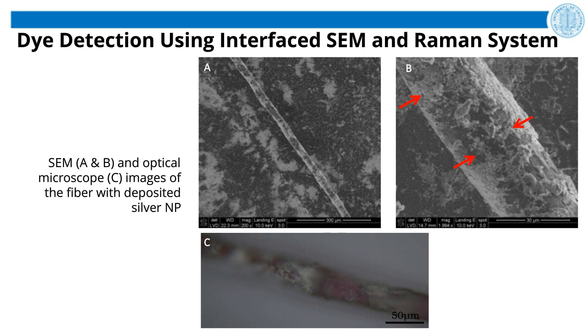Surface-enhanced Raman signal technique can be considered as a powerful extension of Raman spectroscopy. It was discovered that the Raman response can be significantly enhanced up to, say, 8 orders of magnitude and higher in the presence of some metal nanoparticles deposited directly on the surface of the analyte. However, the difficulty with SERS analysis is that it's hard to provide the required good contact between the analyte and metal nanoparticles to excite the plasmon, which is responsible for the strong Raman response. Due to that reason, the SERS results are often not very consistent.